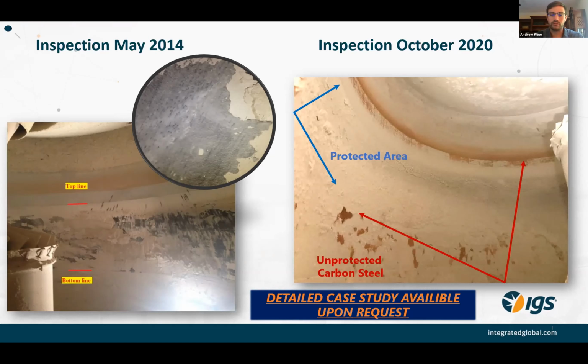Something that's important to note is with a corrosion application, which is much different than an erosion application in this sense, if something's going to fail, it's going to fail relatively quickly for the most part. There's some cases that can saturate materials and things like that over time that will cause longer failures. But in the expected lifetime of the material, if you're going to have a failure, you're going to see it very soon. So that was a good indicator from the beginning.